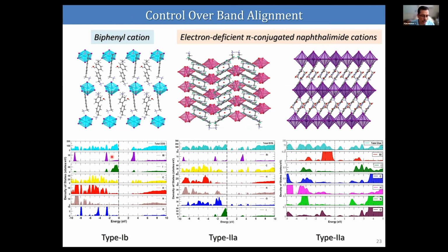And you can see there is no contribution from the organic component in the total density of states in the first material. My friend at IIT Indore did the theory calculation, and they found a type 1B alignment in the material with the biphenyl cation, and there is no proper pi stacking in the biphenyl cation, that again is detrimental to the overall charge carrier mobility of the material. But in the second and third cases, they not only form the type 2A band alignment, that is the organic components are contributing to the band alignment, but in addition to that, they are forming a very stable self-assembled structure. So this can easily transport the charge carriers along one direction. So that is very, very important for the device application.